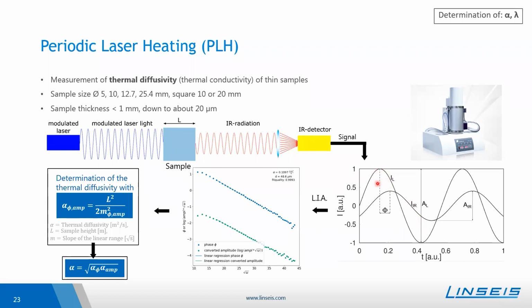However, one can observe a phase shift, and one can detect a difference in amplitude. This is then plotted in a certain way so that in the end there will be a linear relation. From these linear relations from the phase and the amplitude, we find out the slope of this plot here, and this slope will be in the end used for the thermal diffusivity calculation. For the thermal diffusivity calculation, also here the sample thickness is an important parameter.